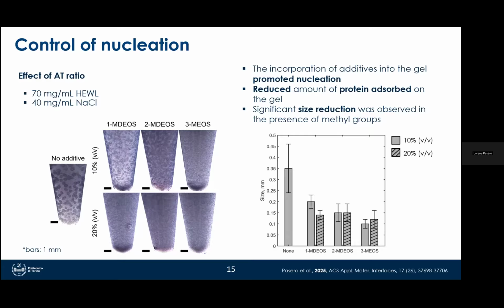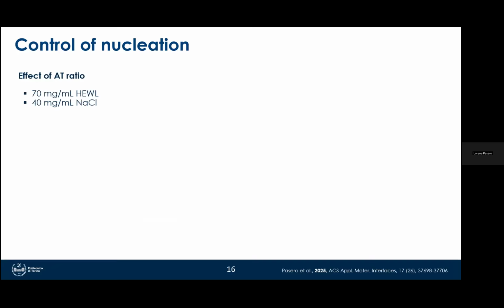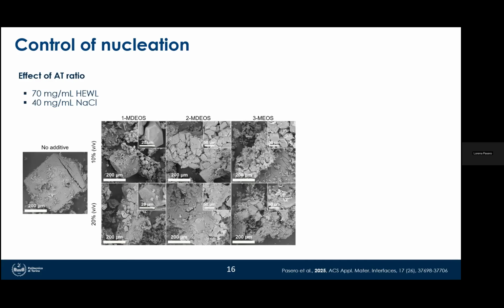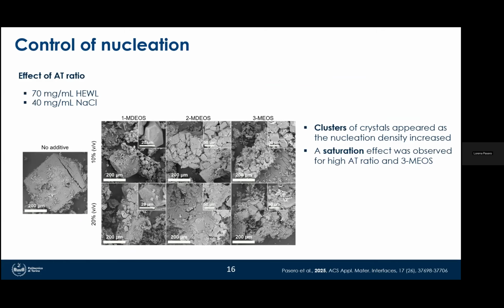The saturation effect can be better observed if we look at the morphology of the crystals by scanning electron microscopy. So here we observed that it was really visible that as the nucleation density increased, we observed clusters of crystals, and the environment reached a plateau where the gel was saturated with protein crystals, and no more single crystals could be observed. So this is why we cannot, let's say, observe significant differences between the 2 methyl groups additive and the 3 methyl groups one.